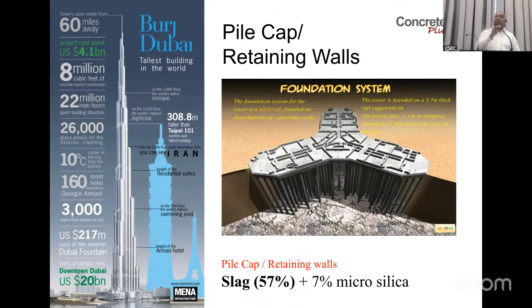Exactly, this is for the thermal effect. Actually you don't want strength in the early days. If you get it, it is an issue. These are very big pile caps, and of course this pile cap will be used after maybe 1 to 2 years at full strength, full load and all the others. In that case, you need a very slow strength gaining curve. So that's why they have used slag.